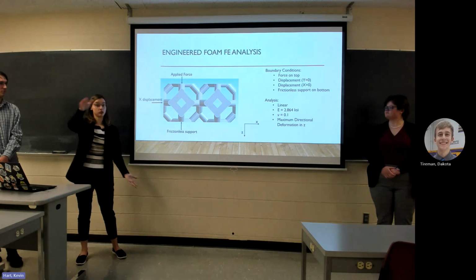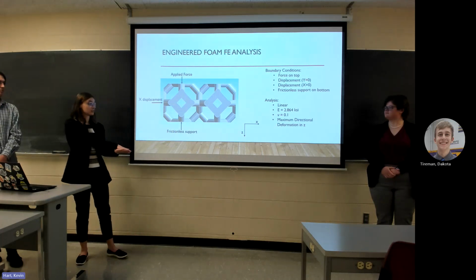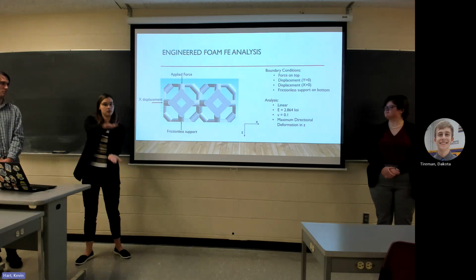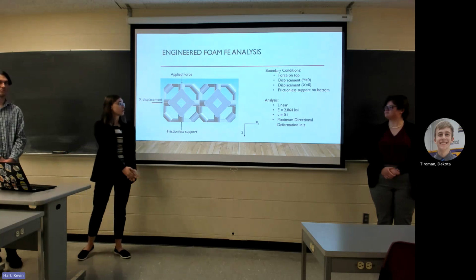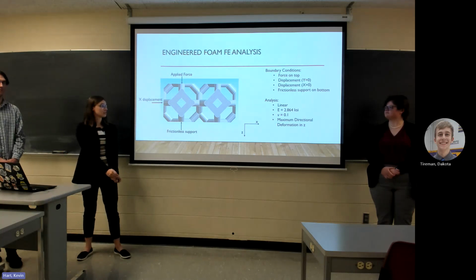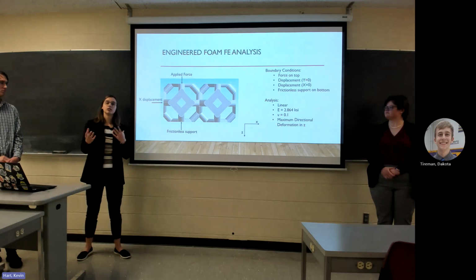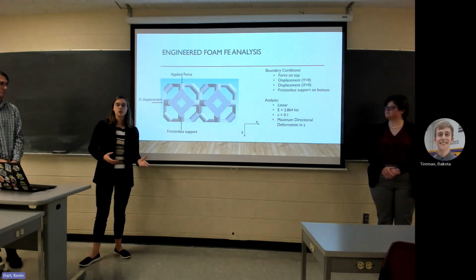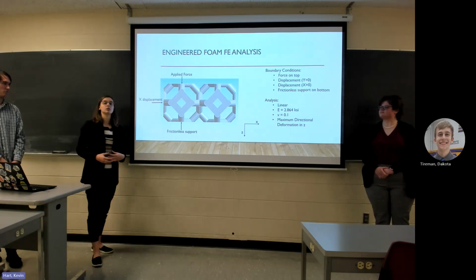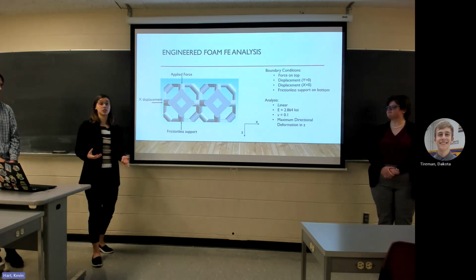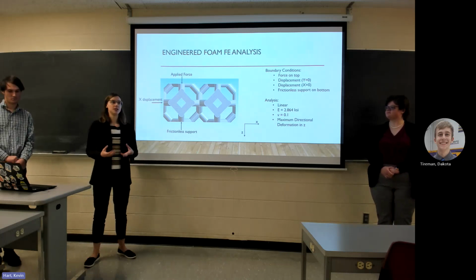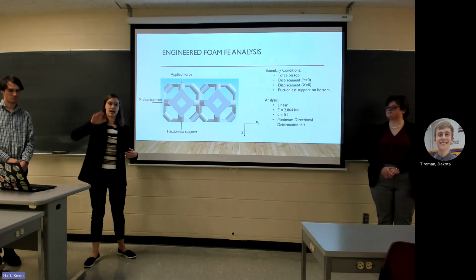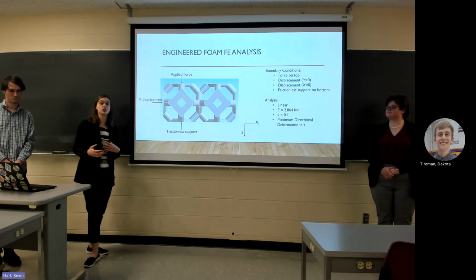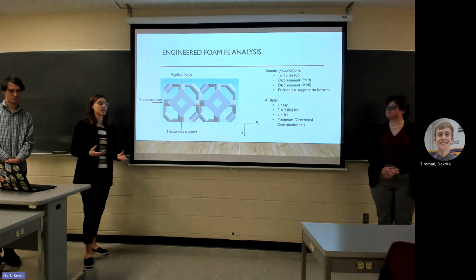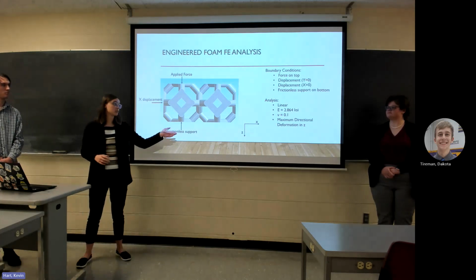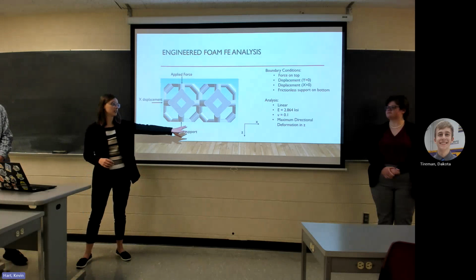That way, when you do it, it actually deforms in the Z direction, because that is what we're worried about, is how does it deform when it's pushed down. So in order to do the analysis on this, we went in between doing nonlinear and linear. So we first started off with doing a nonlinear analysis, and ANSYS was having trouble running the material with that. Because the foam has the relaxation that's happening, ANSYS just couldn't properly mimic what was happening in the test. So we decided to switch to a linear approach.